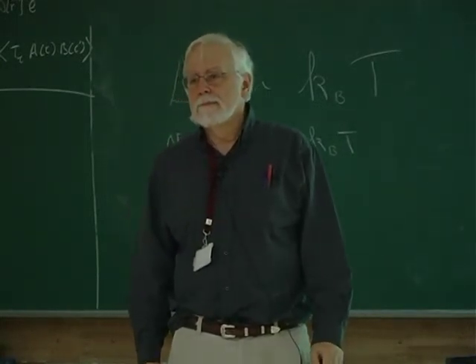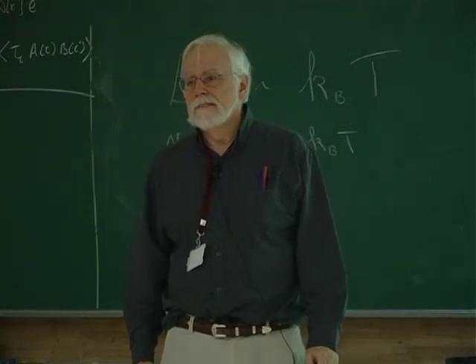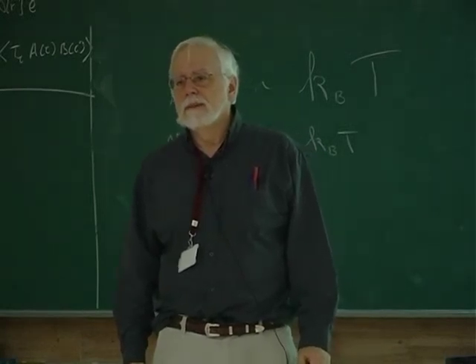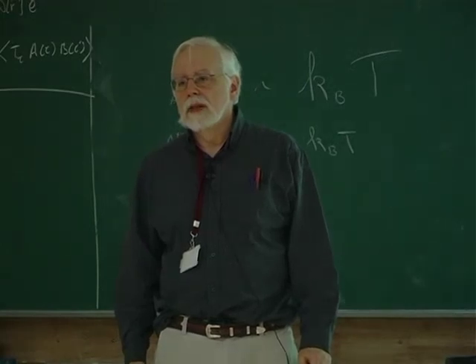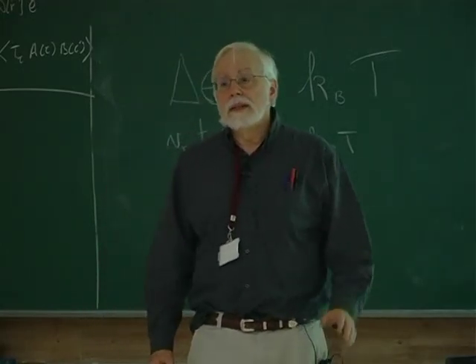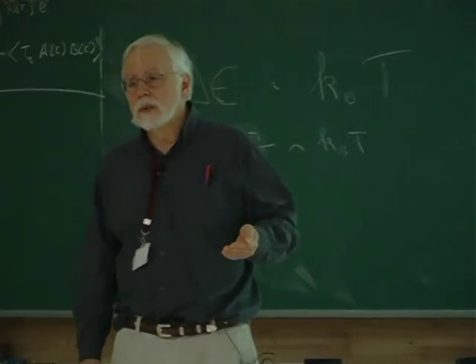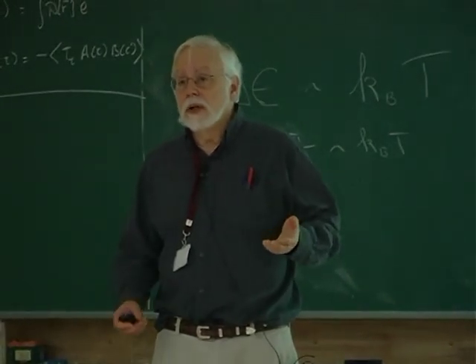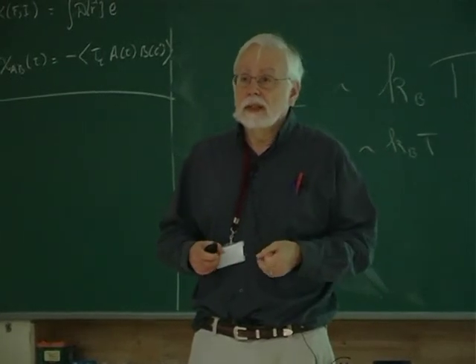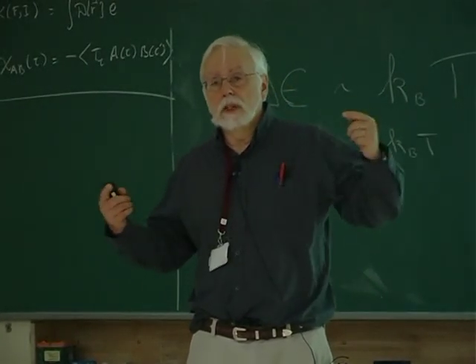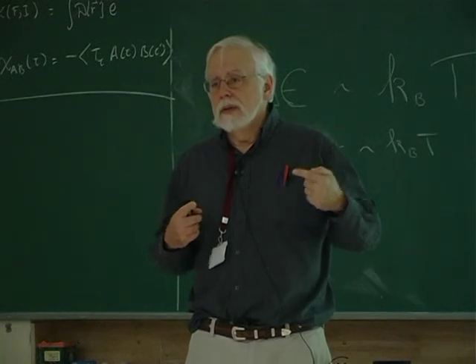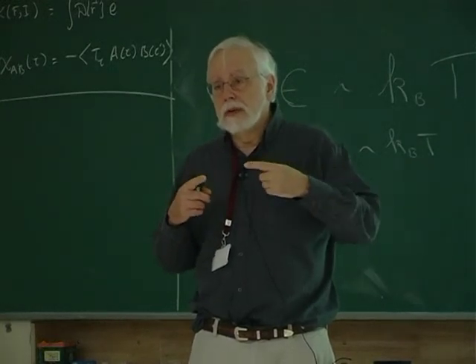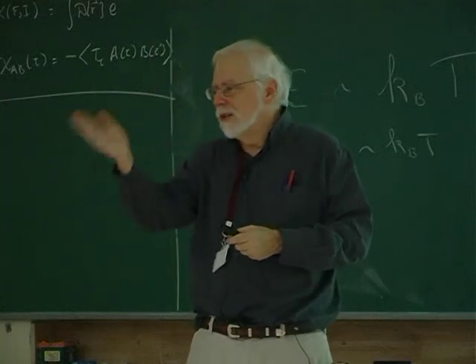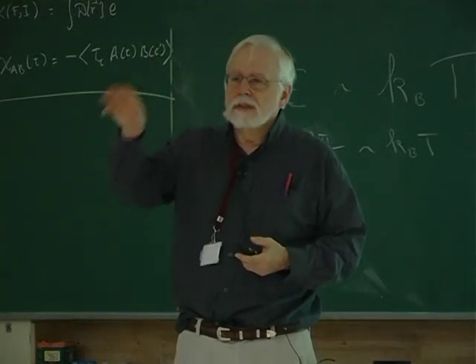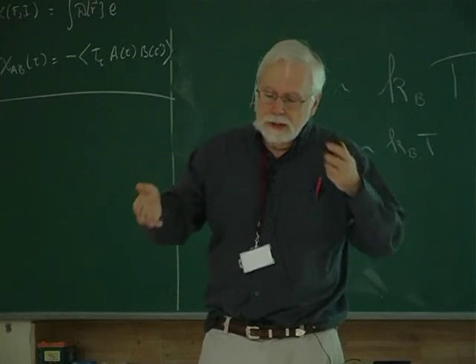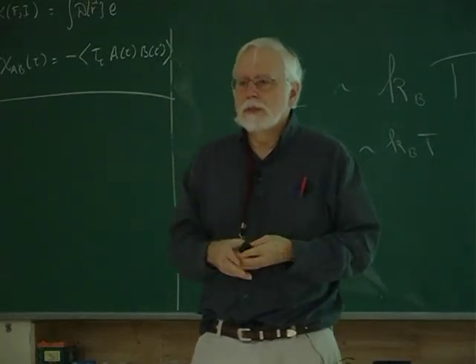And there was one figure which states the disorder dependence of the TC, the fall of TC. What is the percentage of fall with disorder? Is it quite drastic? Well, it's a D-wave superconductor, so it's quite sensitive toward disorder. An S-wave superconductor is not, actually. It's called Anderson's theorem, because you just pair time reversed states. But here, even though you pair time reversed states, there's a sign change when you scatter, and that mixes plus and minus, and it destroys superconductivity.